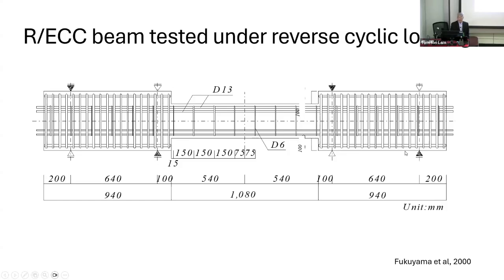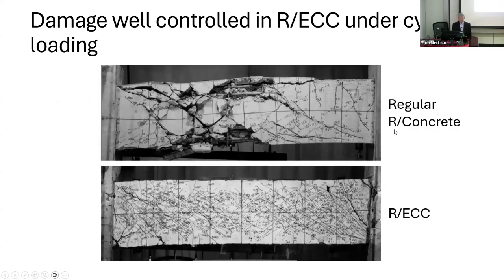So this is a fully reversed cyclic shear loading of the beam in the middle, okay? And it's compared with regular reinforced concrete beams. So you can compare the two after the same kind of loading, fully reversed cyclic loading. The full reversal is responsible for the 2 sets of diagonal cracks, okay? And with the reinforced concrete, you see that the cracks become so large that they expose the steel reinforcement, whereas the reinforced ECC has very tight crack widths. In fact, if the student did not paint the micro cracks, it's very hard to find them.